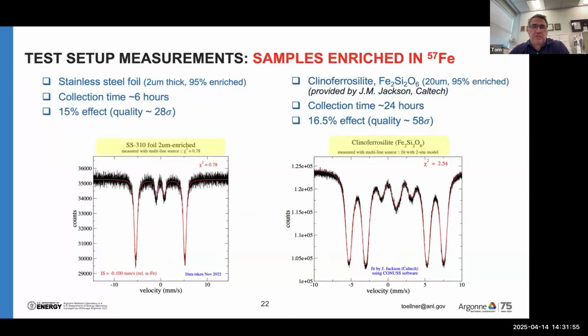So the test setup results, these are some enriched samples I measured. This is a stainless steel foil on the left. This is a 2 micron thick, enriched foil. This collected for 6 hours. Now, the new instrument will have, depending on the line width, assuming it's a 3 gamma line width, this collection time reduced by a factor of 60. And so this 6 hours would turn into 6 minutes. So this would be the quality of spectrum you would get for this kind of material after 6 minutes with the new instrument, assuming a 3 gamma line width.